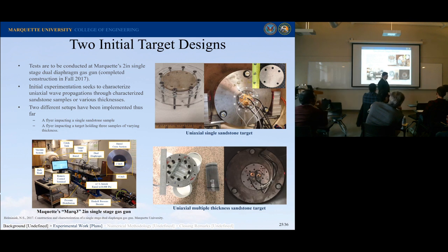What are you measuring in the sandstone? I'm measuring the velocities that are coming out the back. As the waves travel through the material, you get two different things. You get the pressure that's coming out, a particle velocity, and then you also get a time that it takes for the wave to travel through the medium. And those will give you enough information to populate a pressure specific density regime. And that will be used for an equation of state.